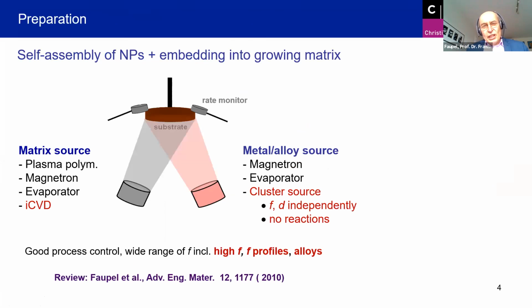Yeah. Over the years, we applied several preparation techniques for the nanocomposites. The simple approach we were mostly using was to have two sources for vapor phase deposition, one source for the matrix component. This could be, as I mentioned already, sputtering for ceramic materials. Recently, and this will be the focus today, initiated chemical vapor deposition for organic materials. And for the metallic component, we also use conventional deposition techniques like magnetron sputtering or evaporation. But recently, we focus on cluster sources, which allow us to independently control filling factor and particle size.